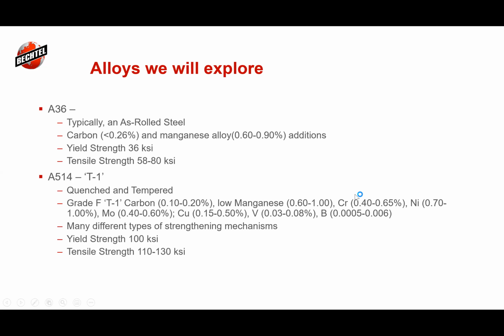Nickel, it has around a little less than 1% nickel. Molybdenum, which is a very high strengthening. It can really add to hardness. It also adds to strength. Copper for some corrosion resistance and some wear resistance.